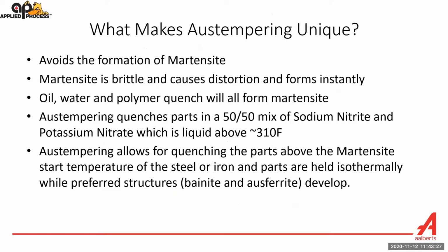It avoids the formation of martensite. Martensite's brittle, and it causes distortion because it is what's called a body-centered tetragonal crystal structure. Oil, water, and polymer quench are all going to form martensite. Austempering quenches the parts in a 50-50 mix of sodium nitrite and potassium nitrate, which is typical, which is first liquid above 310 degrees Fahrenheit. So we're quenching at high temperatures.